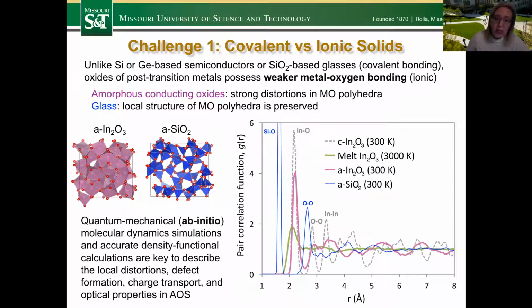And this can be seen right here, that the second peak, the oxygen peak, is suppressed, which tells us right away that we have very strong distortions in the metal-oxygen polyhedra. So the first peak survives when we go to the amorphous phase, but after that all the features are suppressed, including even the second peak that is a feature of the glasses, for example.